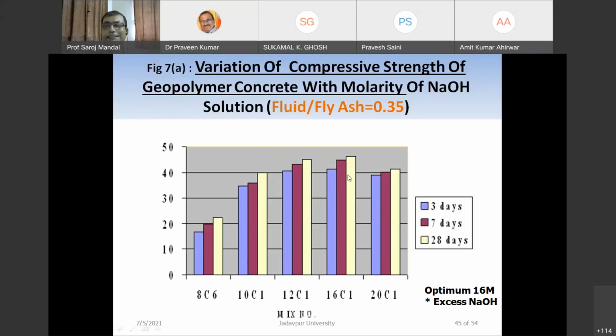But after 16, there is a decrease in strength. And why the decrease in strength? That is also a question, right? Now, what we think is that at 16 molarity, we get an optimum value. Now, why are we getting optimum values? I have already told you that in a particular mix, we have a certain amount of fly ash, and to activate the fly ash, we need a certain amount of alkali.